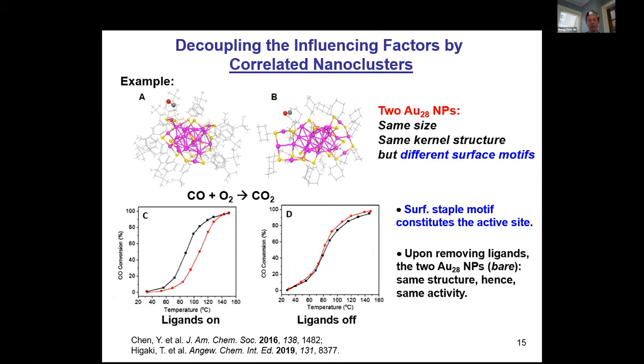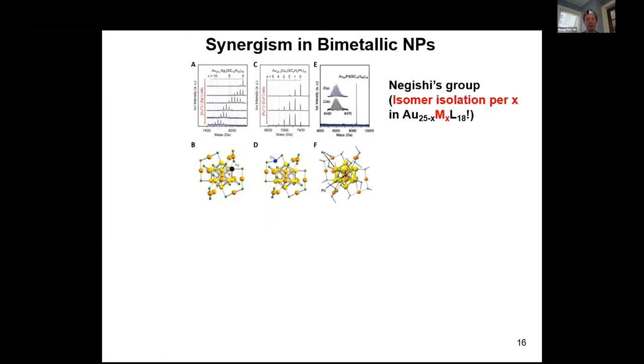So you can really look into the effect of that particular factor, for example, whatever surface structure or size. And then, as Professor Shah mentioned, bimetallic nanoparticles are particularly attractive in catalysis. So in the field of atomic precise nanoparticles, the Negishi group have done very impressive work. They were able to even isolate different isomers. For example, let's say 2 Ag atoms doped into gold-25, and then they were able to isolate the different isomers.